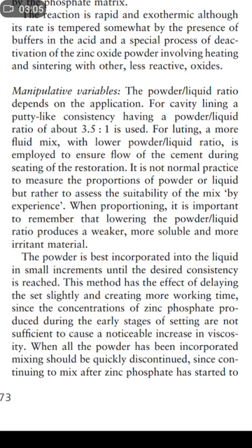It is not normal practice to measure the proportion of the powder or liquid, but rather to assess the suitability of the mix by experience. When proportioning, it is important to remember that lowering the powder to liquid ratio produces a weaker, more soluble and more irritant material.